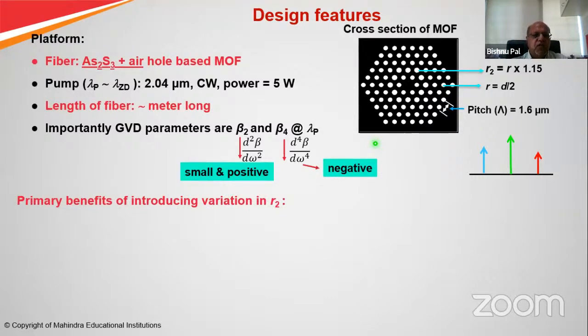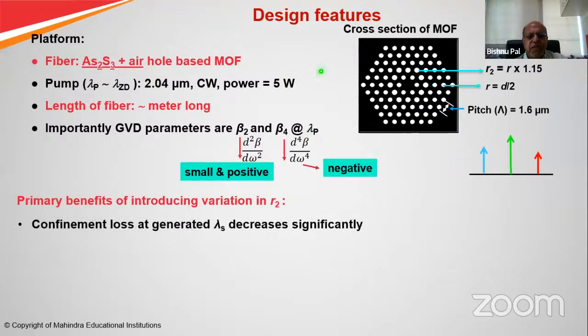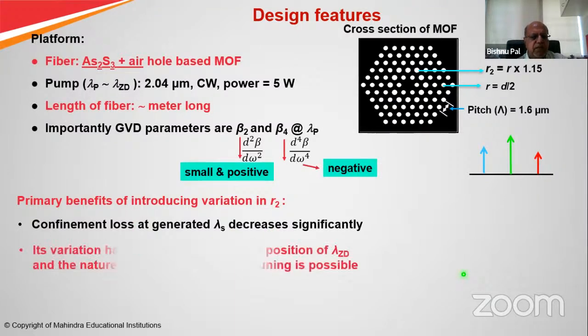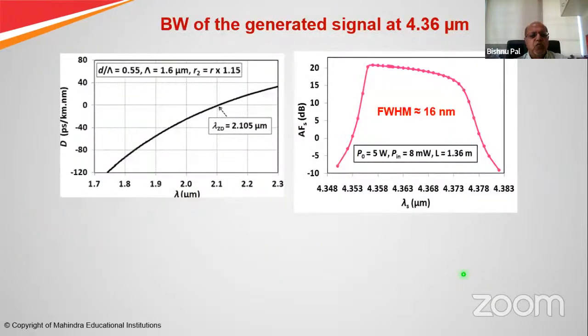mid-IR light source. So there are benefits of the slightly different R2, because the confinement loss at the generated signal decreases significantly because of this, and its variation has negligible effect on the position of λZD and the nature of the dispersion curve. So fine tuning is possible. It's all explainable in terms of physics, but we do not have so much time to go through so many details. I've given you the paper reference. Everything is explained there. The full width half maximum is about 16 nanometer, around 4.36 micrometer.